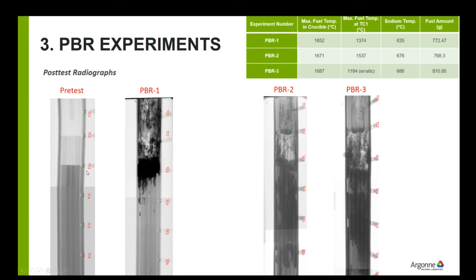And this is the pre-test radiograph of the pin bundle test section. In the PBR1 experiment, as you can see, we didn't use a guide funnel, and we just dropped fuel onto the top of the claddings. So some of the uranium dropped into the coolant channel directly, and some of the uranium entered the claddings and then breached the cladding by eutectic formation and entered the coolant channel. Because pure uranium has a higher freezing temperature than the eutectic between uranium and cladding, it quickly froze near TC3, and the penetration or dispersion of this uranium was lower compared to the other experiments. So most of the uranium was found frozen near TC3, thermocouple 3.